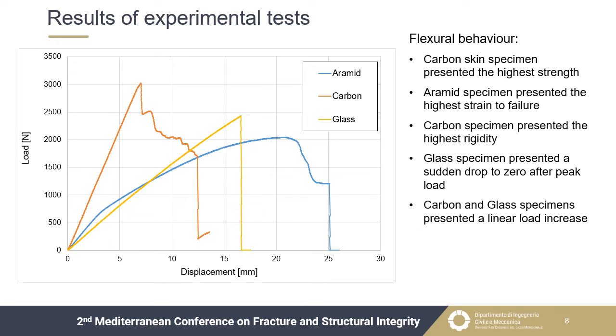with a value of less than 2100 Newton. As concerns the maximum displacement, the highest value was reached by the aramid specimen, and it was 21 mm, while the lowest value belonged to the carbon specimen, and it was 7 mm. The curves of the carbon and the glass specimens were characterized by a linear load increase, and the latter presented a sudden load drop till zero after the maximum point.